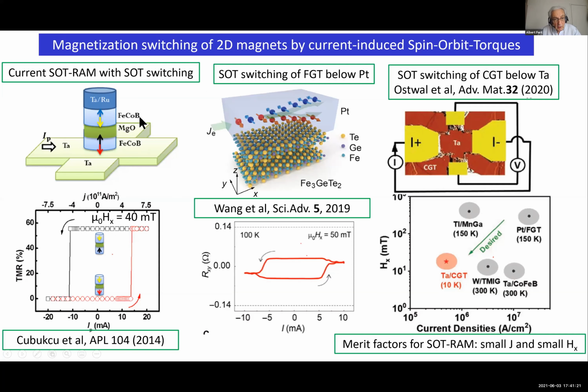So this is a typical example of a result with a 3D magnet, iron cobalt boron, and the same sort of experiments can be performed with 2D magnets, for example, FGT. In these experiments, again, a platinum layer is deposited on FGT, and by applying a current in the platinum layer and exploiting the spin Hall effect to inject a spin current into the FGT, one can obtain similar cycles, that is switching from down to up, and then by reversing the current from up to down. And again, it is necessary to also apply a small in-plane field to break the symmetry and allow the reversal of the magnetization.